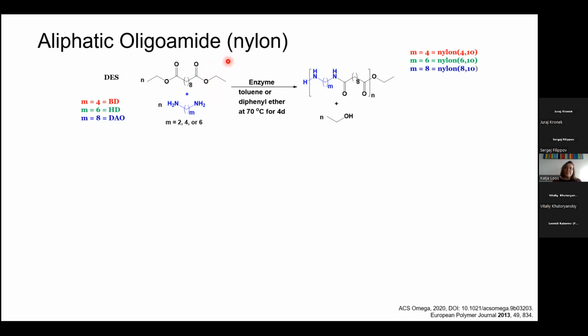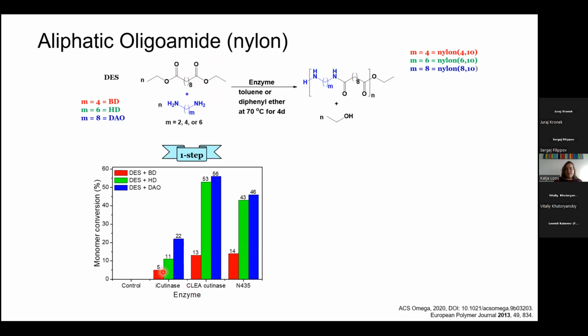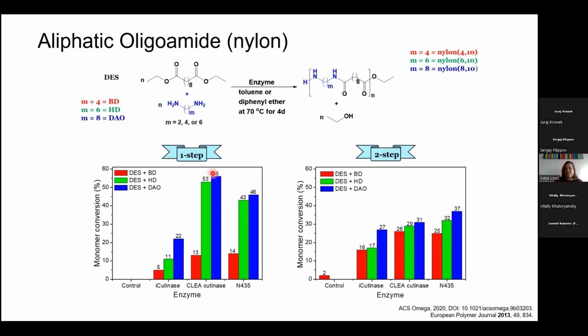And then we don't work with vacuum, and that's why very often we start with an ester group, because as you know, it's easier to remove the methanol or ethanol than the water. But you can also do all this polymerization with the diacids, and it's of course greener because it's more atom efficient. But here you see we screened various aliphatic diamines, and we also used different enzymes. Cutinase is also a hydrolase, and we do different immobilizations of the cutinase and the acrylic bead immobilized Novozym 435. And then we do one-step and two-step polycondensations, and then we get different results. We also get different microstructure. We also get different end groups.